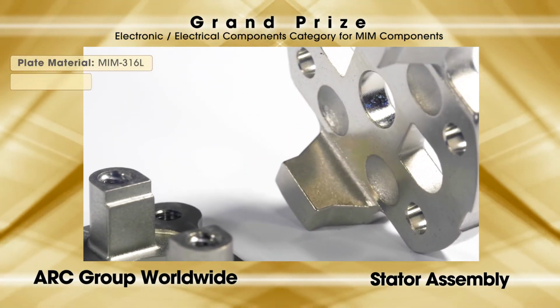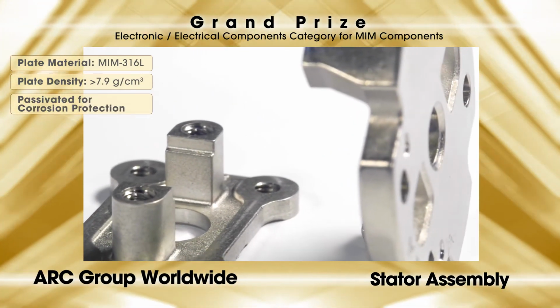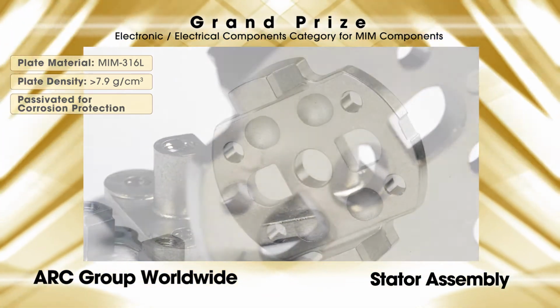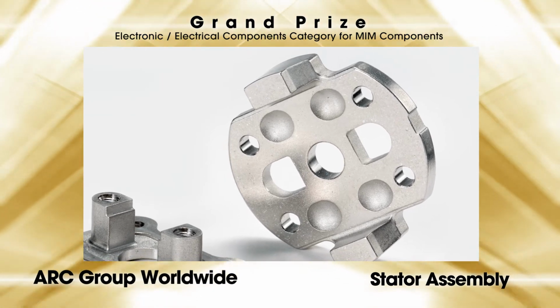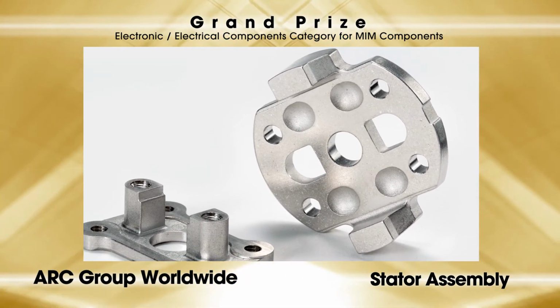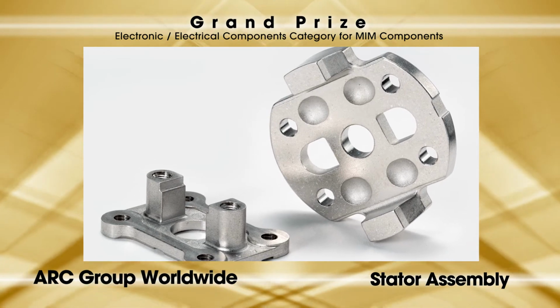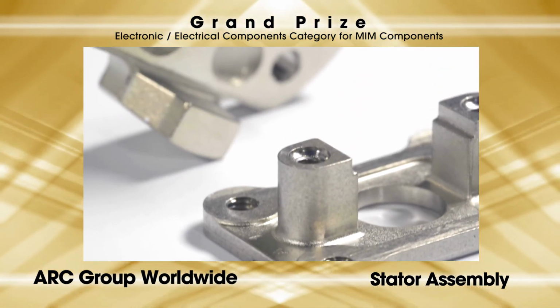The plate is made from MIM 316L with a proprietary binder formulation to ensure even and complete sintering with minimal distortion. The part sinters to 99% relative density with minimal distortion and does not require HIP processing. Minor machining is required on the bottom and top surfaces to maintain profile and hole positions. The two screw holes are reamed and threaded and have screw thread inserts added to provide strength in the final assembly. The parts are passivated for corrosion protection.